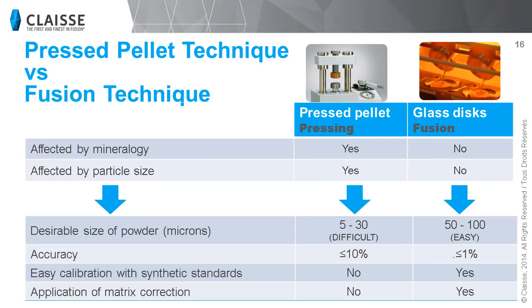This table summarizes the benefits of sample preparation by fusion compared to pressed pellet. As we discussed, using fusion eliminates the particle size and mineralogical effect. It leads to the following benefits: less grinding prior to sample preparation, increased accuracy, possibility of using synthetic standards for calibration, a wider calibration range, and application of matrix correction.